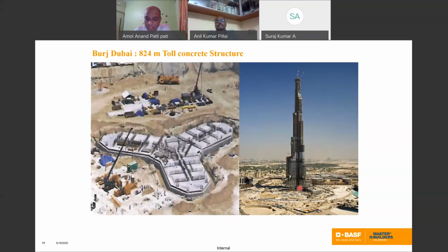If I calculate the amount of concrete in the pipeline at a time, it is around 11.5 cubic meters, the concrete inside the pipeline from the pumping end to the delivery end. So 11.5 cubic meters of concrete multiplied by a concrete density of 2,500 kg per cubic meter, the total weight of the concrete in the pipeline is around 28 metric tons. Right?